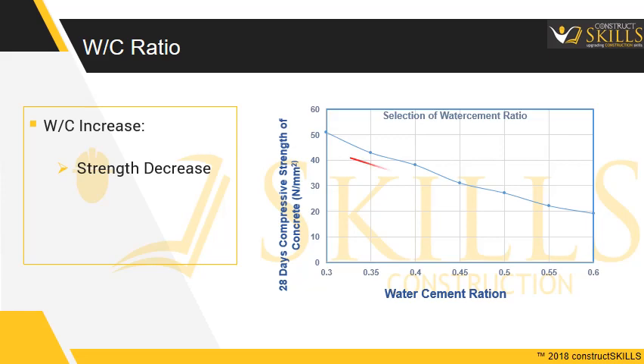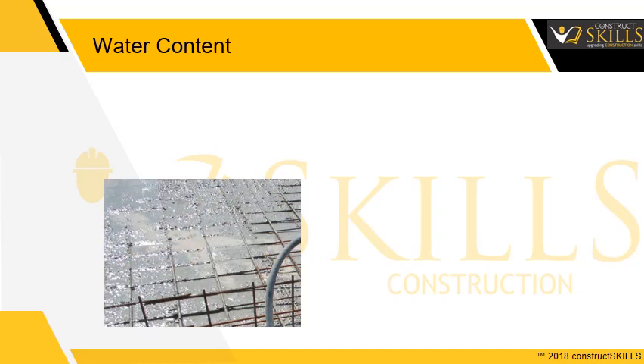Water rise causes weak planes between each layer of concrete deposited. In horizontal surfaces such as floor slabs, excess water rises and causes a weak laitance layer at the top. This layer suffers from loss of strength, low abrasion resistance, high shrinkage, and generally poor quality. Excess water can be identified if evidence of water rise (vertical segregation) or water flow (horizontal segregation) occurs.